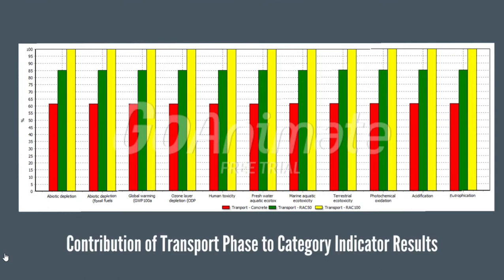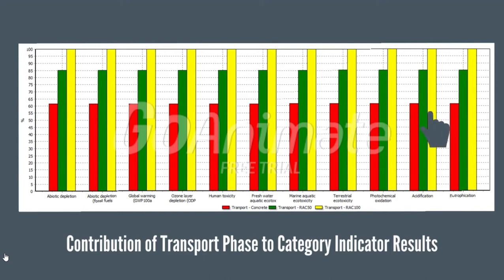On the other hand, conventional concrete evidently has the lowest impact compared to both RAC-50 and RAC-100. Based from the inventory, the distance of the quarrying site and cement production to any point of Metro Manila gives a good environmental impact which does not require long travel. However, the production of RAC gives additional transportation requirements because of its delivery from demolition site to landfill and then to the construction site. As a result, conventional concrete has approximately 23% and 38% lower impact in all categories for the transport phase compared to RAC-50 and RAC-100, respectively.